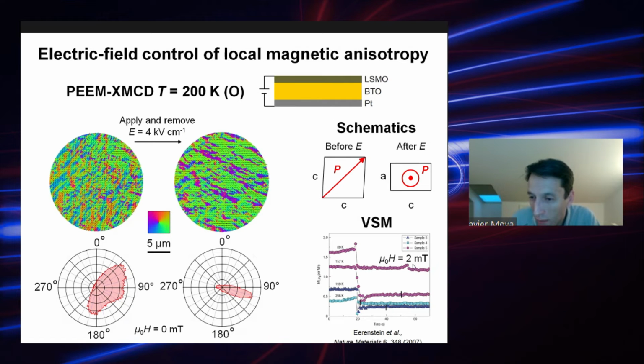But notice that this was measured at very small magnetic field, 2 millitesla, which means that the magnetic field was not able to align the magnetization, because otherwise you will not see this big change. You will see really nothing. And the explanation is precisely this: that when you apply an electric field, you can rotate the magnetization 90 degrees in many places. So if you are measuring along this direction, and then you rotate the magnetization 90 degrees, the component that you measure in the magnetometer is going to be much smaller. So this is why you see this.